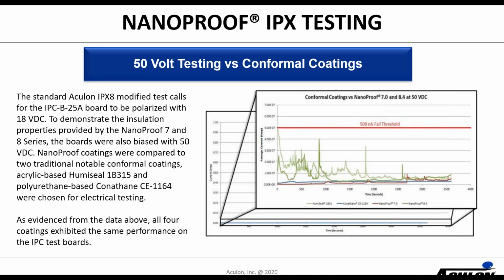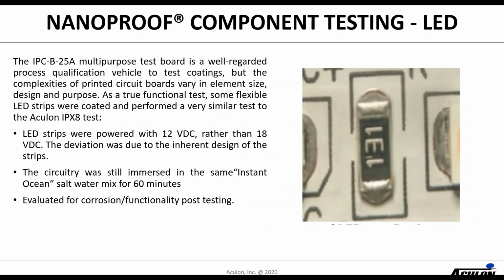So in addition, what we had done is to compare to conformal coatings, which we know are typically failing IPX7 IPX testing. We compared these coatings on the IPC test board and then found that they tested well on the IPC test boards as well. So you can see here that the nanoproof coatings, in addition to traditional conformal coatings, all stay below the 500 nanoampere failure thresholds. While we know in a real world example, the conformal coatings are by no means up to IPX7, IPX8 levels.